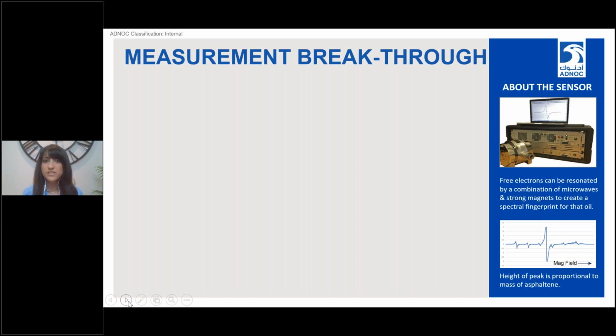So how could we use it? Basically, if we have the sensor reading the fluids coming from our wells, and we're getting a stable signal, it's telling me, okay, the asphaltene concentration is steady, so there's no issue. However, when this signal starts to change, for example, starts to drop, it's indicating that the asphaltene concentration in my fluid is dropping. So I'm losing part of that asphaltene somewhere along the system, probably in my well. And that gives us the early indication that we're looking for.